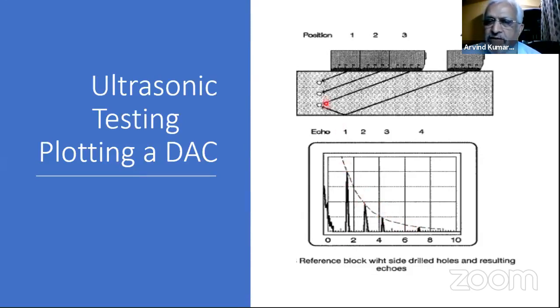What is the implication of this? This is the defect here, which is very close to the probe, and it gives me this much amplitude. Now, if I pick up the same defect at a different beam path, with the probe somewhere else, the size of the hole is the same. But because I have traveled so much inside, there are losses due to absorption and scattering, which give me a lower indication. So what I get here as a peak after traveling so much distance, and what I get here as a peak after traveling only this much distance, my defect size is the same.